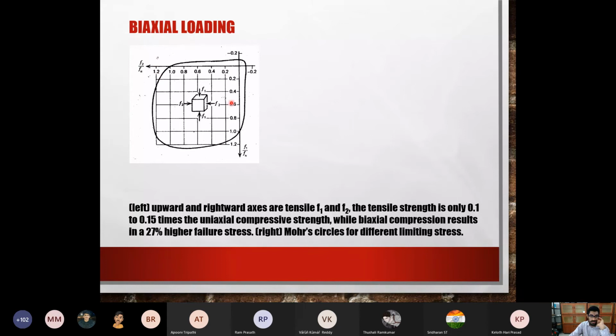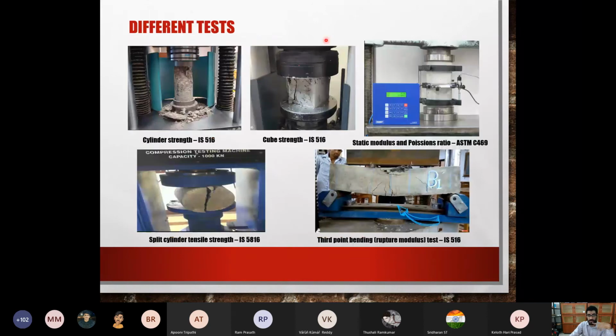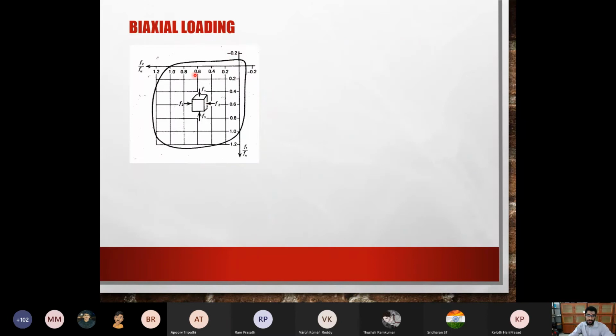So this quadrant that you see over here is marking the envelope of the stresses when both F1 and F2 are compressive. When both F1 and F2 are compressive, you see that your concrete can actually reach a strength which is greater than the uniaxial compressive strength. Fu is your uniaxial compressive strength, meaning that this test which you did over here, you may have got some strength, say M25 and you got 25 MPa as a strength. If you actually do a biaxial compression like this, then the strength which you will get will not be 25, it will be 25 times 1.2. So when you do a biaxial loading, the strength has increased.